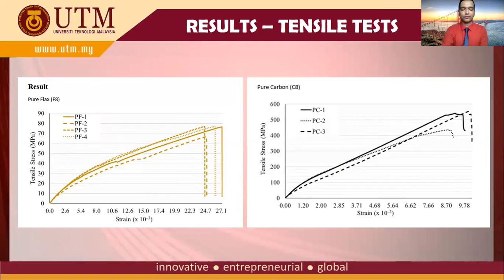Here is the result of tensile test. On the left hand side is the result of pure flex. As you can see, the maximum tensile stress can go up to nearly 80 megapascal. All the curves have similar trend. On the right hand side, the result of pure carbon, the tensile stress can go up to nearly 550 megapascal. However, in this test, there are only 3 curves that can be obtained because there is an error with the specimen. Result could not be obtained.